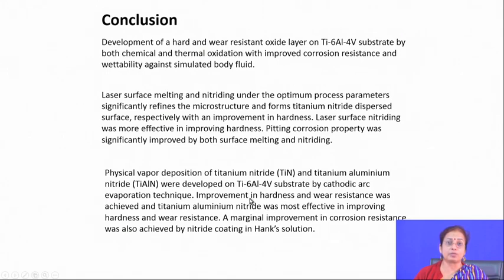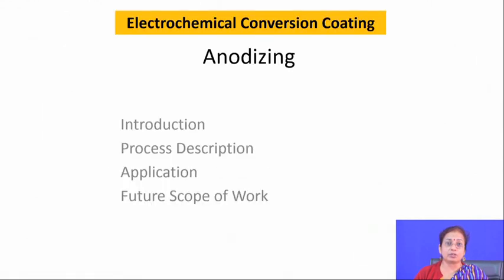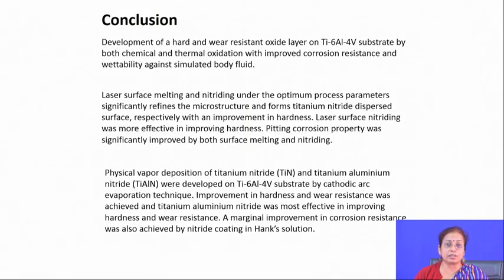So, in both the cases we improve the hardness and wear resistance to a large extent, and biocompatibility enhancement is also there. These are a few important notable results, and this chemical conversion coating is a very important route for improving the hardness and wear resistance and other properties like corrosion properties and bioactivity of the surface of metallic materials. But you can choose any route, as I mentioned: the thermal route, the simple chemical low temperature route, or the laser processing route to have that layer on the surface. But you have to be careful in optimization of process parameters, so that whatever results you are looking for are obtained on the surface for the desired applications.